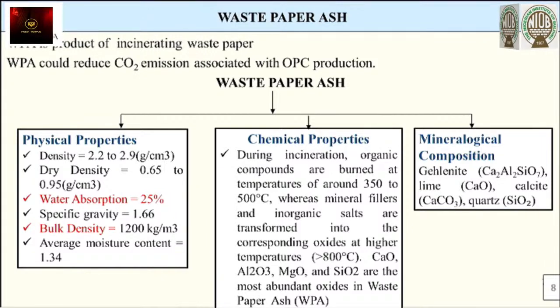Now, if you check the chemical analysis for the waste paper ash, during the incineration of the waste paper, the organic compounds are burned at a temperature of about 350 to 500 degrees Celsius, where all the mineral fillers and inorganic salts are transformed into corresponding oxides. Now, you can see the oxides, aluminum and silicate oxides. All this makes waste paper ash a good pozzolanic material because of its chemical content. Also, for the mineralogical composition, we have gehlenite, lime, calcite, and CaCO3. Next slide, please.